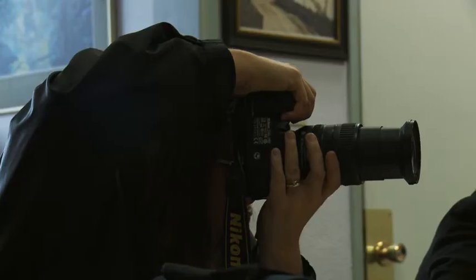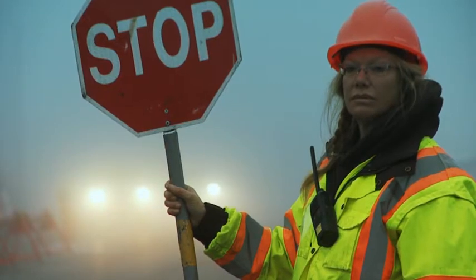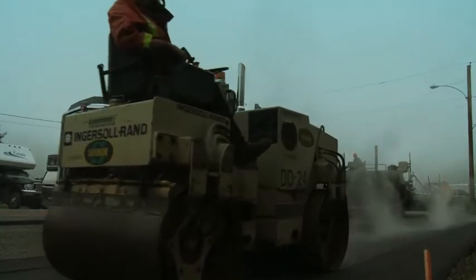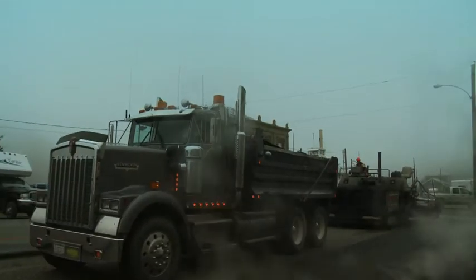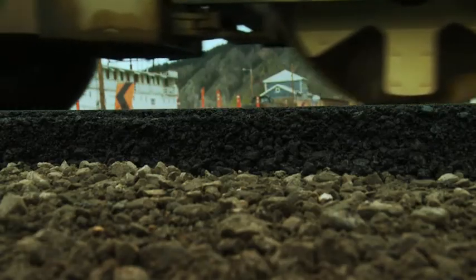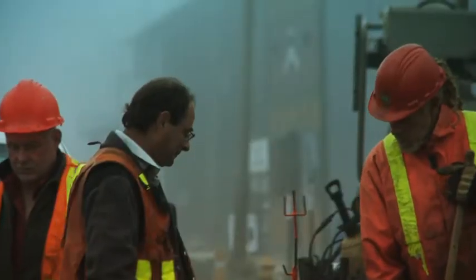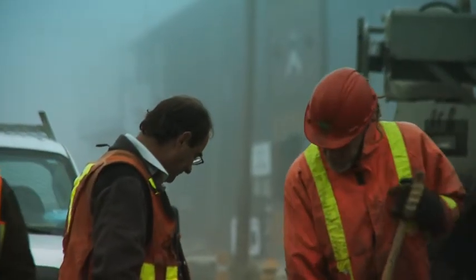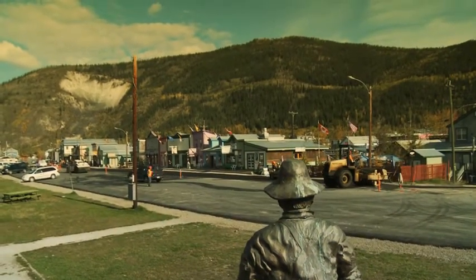While the Bituclair project got some media coverage in Whitehorse, a testimonial to the crucial permafrost issue in the Yukon, conventional paving work had already started in Dawson City. A 75-millimeter layer of asphalt was laid on the foundation of Front Street. A 25-millimeter layer of Bituclair would be applied afterward in order to reflect solar heat and provide a rustic, rugged look that was desired by Dawson City's Historical Society.